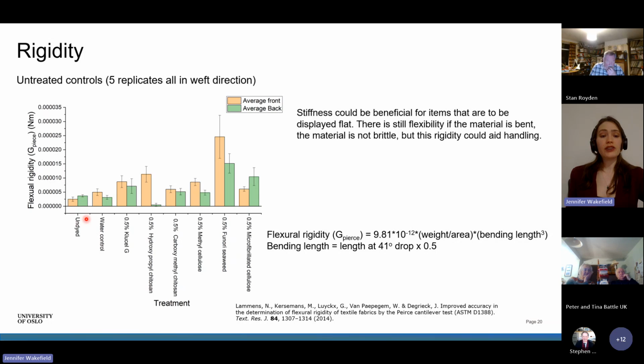If you look at the undyed, the lowest numbers represent the most flexible material. These were very, very flexible. When you add Klucel G, you've got a slight increase in stiffness, but the Funori by far resulted in the biggest increase in stiffness. This stiffness could be very beneficial when items are to be laid flat, because you'll be able to turn them over without bits that are loose bending under their own weight and potentially breaking because of the brittle nature. So this could allow for more handling, and this is important for exhibitions and also for research purposes.